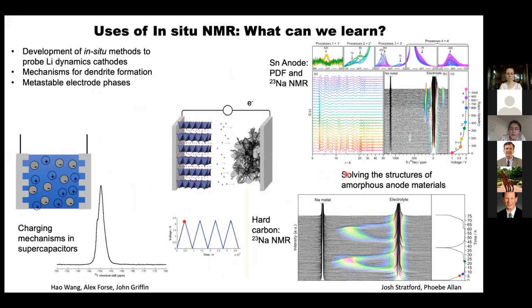This is an overview of the sodium space. I just wanted to start by showing you what we've done in that area, to remind you that in sodium chemistry, you can't use graphite, and what you use is this hard carbon. And so by just doing sodium NMR of this hard carbon, we can unpick the different processes that go on. And then you look at the electrochemistry, and you can relate the electrochemistry to the local environment as seen by the sodium. And what you're seeing in this sloping process is the sodium that goes in, and it's in more diamagnetic environments near defects. And then in this flat process, close to sodium plating, the sodium actually fills the pores or the holes within the hard carbon, and it forms sodium metal. And then you see this dramatic shift of the peak towards the position of where sodium metal is.